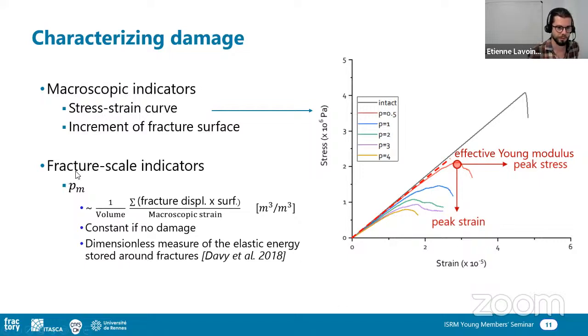And we also have the possibility, because this is numerical analysis, to perform more specific analysis using a fracture scale indicator, an indicator that we call PM that we developed, that can be defined from subcontacts that belong to a fracture, and that is a function of the fracture displacement multiplied by the fracture surface divided by the macroscopic strain.